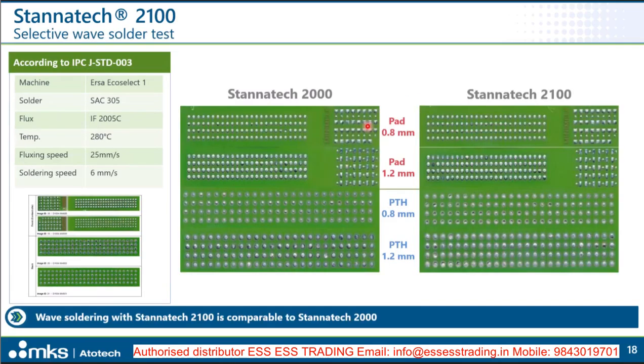So these were all solder printing tests where we print the solder depot, do the reflow, and then check the wettability. Another approach is to have liquid solder and splash the liquid solder onto the panel and check the wetting of the solder on the pads and PTHs. So this is the selective wave soldering test.